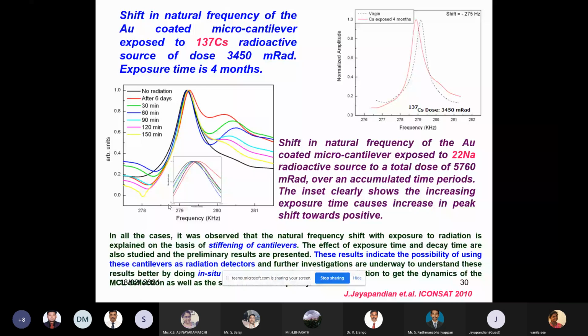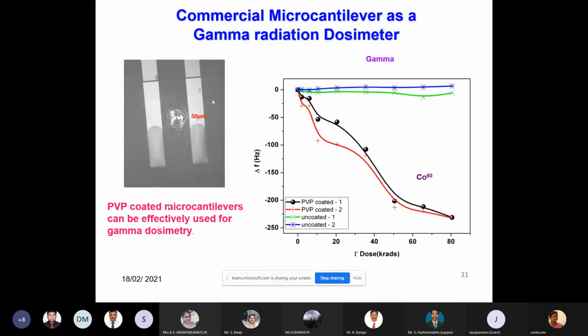People are working out in detail the reason for that. This inset shows the variation, how the amplitude peak shifts for various exposure times. This confirms that stiffening of the cantilever is the main reason, and the stiffness is due to stress from the photoelectric effect. Radiating with charged particles or gamma rays stiffens the cantilever, shifting the resonance frequency, and that shift can be recorded. Then one can use the cantilever as a radiation sensor, both quantitatively and qualitatively.